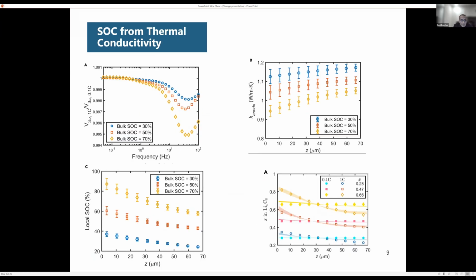Once I do that, now what we do is a very fast charging, and then we do the same thermal wave measurement at fast charging, 10x, right? 1C, which is 10 times faster than 0.1 C. And then again, we compare the ratio of the 1C versus 0.1 C, and you can see a big difference depending on the frequency, right? By fitting a model, now I can back calculate K anode as a function of Z, okay, for different states of charge, right? So I have now K anode as a function of Z,